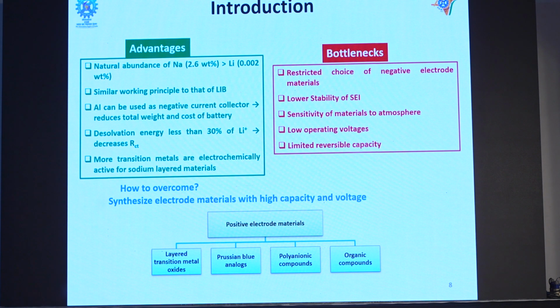If you have a sodium ion battery and a lithium ion battery, and you want the same energy density, for a lithium ion battery you can have a very small pack like this. For the sodium ion battery, it will take a huge size, like a load carrier. You know, in the old movies we see these load carriers. It occupies such a space. So the energy density is very low for a sodium ion battery when the capacity is very low.